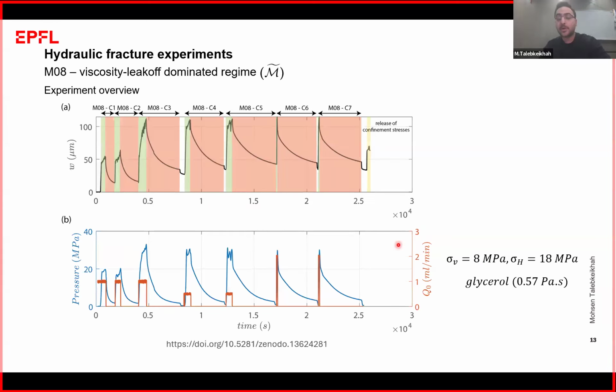So now it's time to check the other experiment that has been done by injection of glycerol with lower viscosity than the previous experiment. In this experiment, we did 7 cycles of injection and closure, injection and closure, injection and closure. And let me say to you that after all these 7 cycles, the fracture remains inside the block, and it didn't reach the boundary of the sample. Here also we see this residual opening that remains inside the fracture even after the experiment and even after we release the confinement stress. I want you to pay attention to the pressure values.